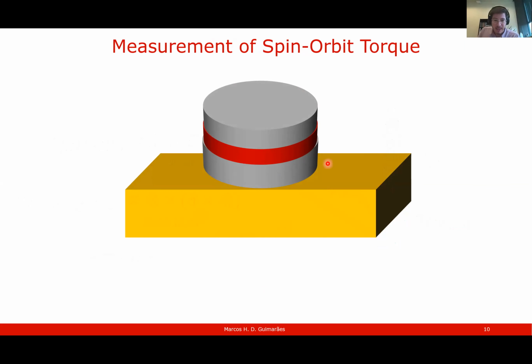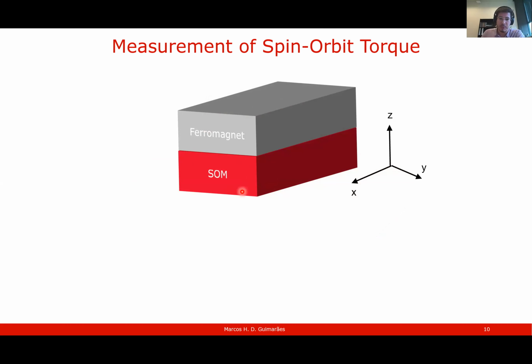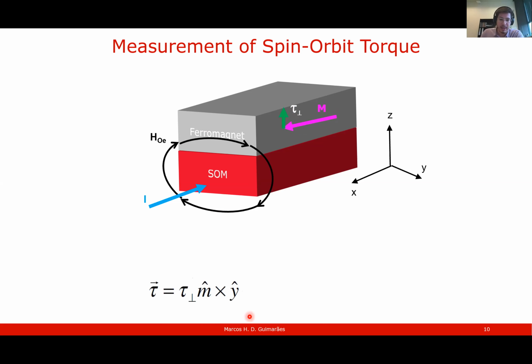So how do we measure spin orbit torque? Here I'm bringing up our basic memory cell from our SOT MRAM. And we are going to use just the bottom part here, just below the barrier. So we have the spin orbit material, so a write line, and the free layer. And it looks like this. So we have the spin orbit material underneath the ferromagnet. Now, if this ferromagnet has a magnetization M here pointing in a certain direction, and we drive a current through this material, this current has a magnetic field associated to it, which is called the Oersted field, and this is basic electrodynamics. If you have a current, you have a magnetic field associated to it that circles around, and this causes a torque out of plane for a magnetization that points in the plane. And again, this can be converted into an M cross Y term, and this is mostly due to this Oersted field.